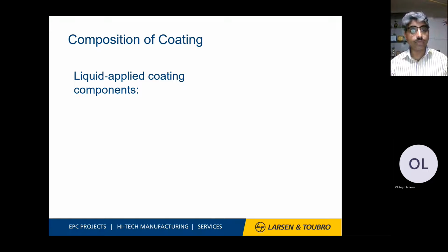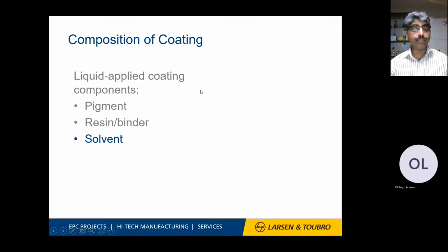Now, people will want to know what are the components a coating normally has? We say coating means one layer, two layer, three layer, multi-layer coating. No, it is not so. When we want to buy the coating, there are many components which contribute to the coating, the liquid applied coating components, normally pigments. This is what the pigment name is given to the coating. Resin or binder, which is added to get it over the surfaces. The sprayed area ratio with respect to different coatings is designed by this. Solvent just gives you the application, and after application, the solvent will vaporize and get into the environment and you find dry film thickness.